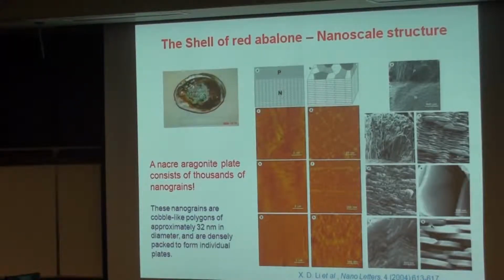And we use atomic force microscope, soft cantilever, self-tuned. You cannot use auto-tune. Look at the cross-section. You can see those bricks stacked together. But if you blow this area up to see individual bricks, you can see they are not single crystals. Inside this brick, there are tons of nanoparticles with a size about 30 nanometers or below.